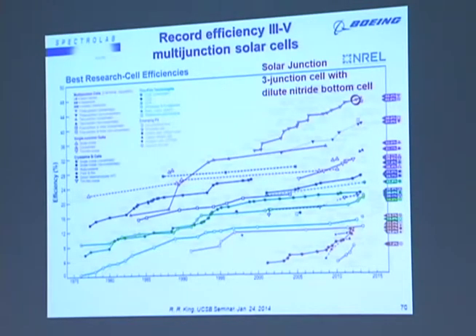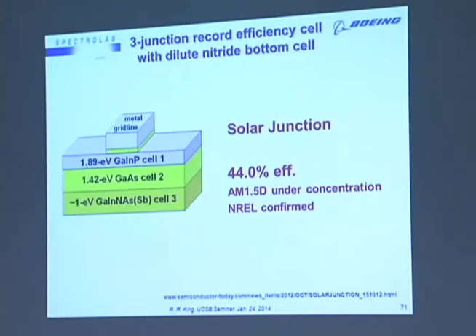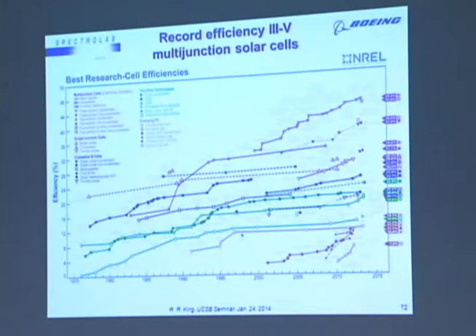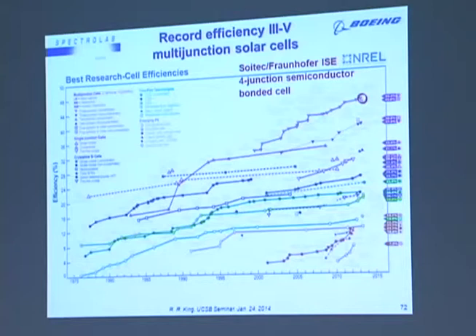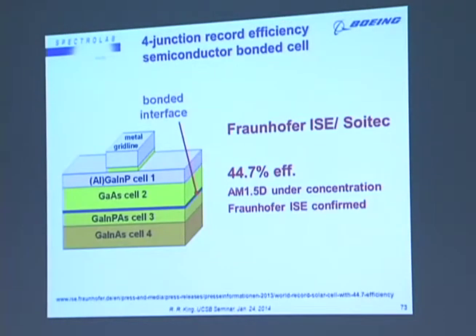Another very interesting recent development has been Solar Junction's 3-junction cell with a dilute nitride bottom cell at 44% efficiency. It has a cell structure like this with gallium indium phosphide, gallium arsenide, and 1 eV dilute nitride on the bottom. And yet another very interesting recent development is the use of wafer bonding that Soitec and Fraunhofer have used to form a 4-junction semiconductor bonded cell. That has reached 44.7% efficiency.